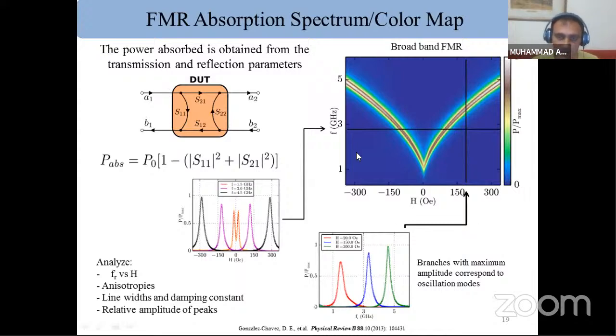Here, after getting the color map, this is the absorption power by the system. You can see we can extract information from this color map by using two methods. Here there is a color scale: blue represents zero, and the maximum power absorbed goes up to one. One method is fixing the frequency and varying the field, like we have varied the field from minus 300 to 300 by fixing the frequency at 1.5, then 3 and 4.5. We got these amplitudes, that is the maximum power. The resonance occurs here, at the maximum power absorption. Similarly, we can fix the field and sweep the frequency.